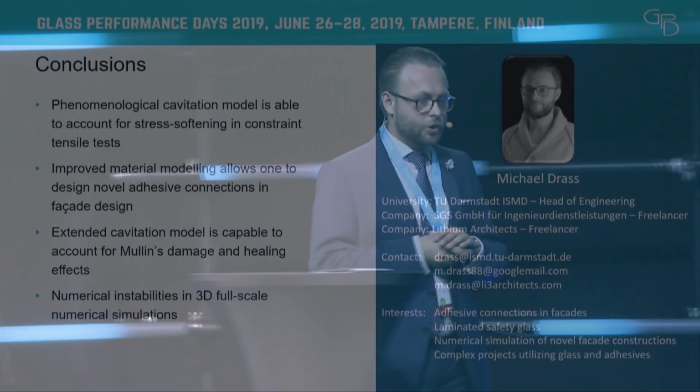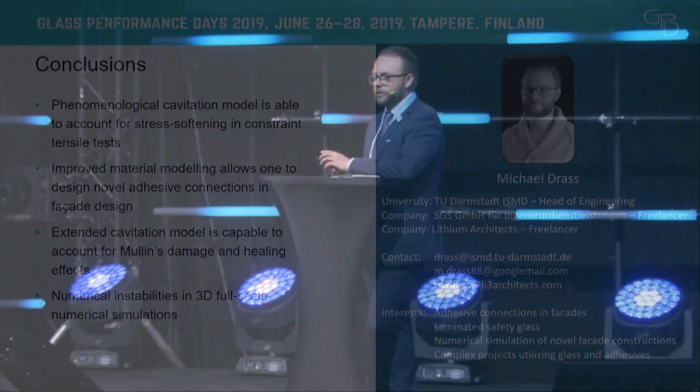So in conclusion, we showed that we have a phenomenological cavitation model which is able to govern the cavitation effect on the virgin loading. We improved this new material model by adding damage variables for the isochoric Mullins effect, for the volumetric Mullins effect, and the volumetric healing effect.